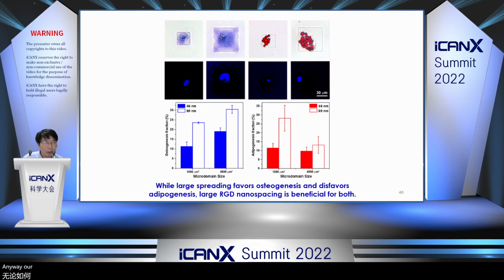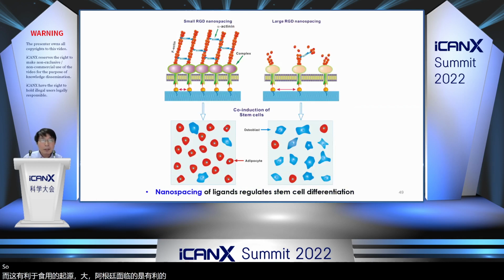Anyway, our conclusion is more deterministic and very interesting. While large spreading favors osteogenesis, and small spreading favors adipogenesis, large RGD nanospacing is beneficial for both. So the RGD nanospacing, why is nanospacing important? We hypothesize that the binding of RGD and integrin is a necessary condition to trigger the specific cell adhesion, but it is not sufficient. The sufficient condition should consider the supramolecular structure of the cytoskeleton.